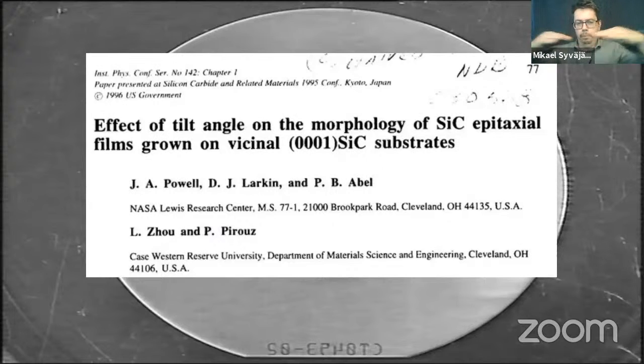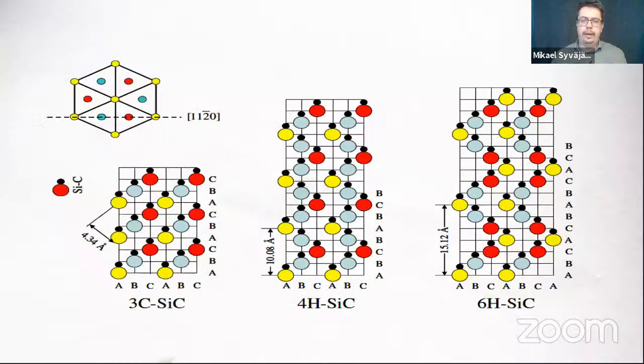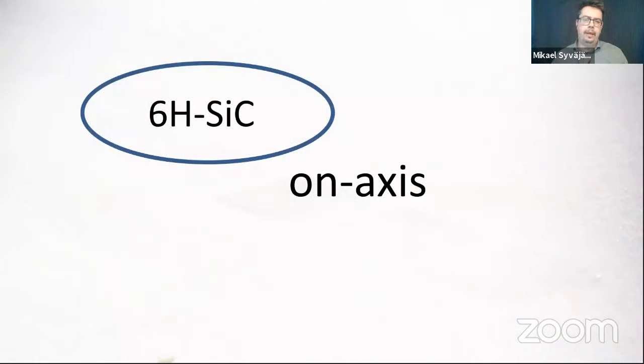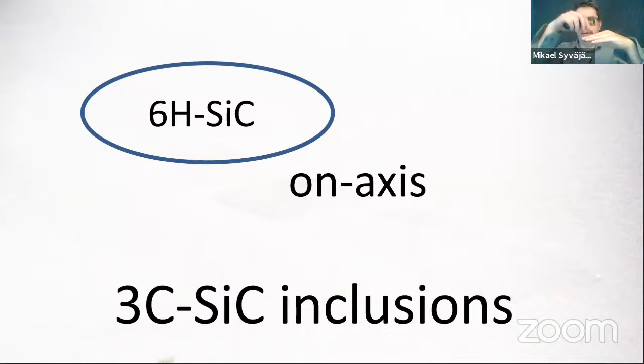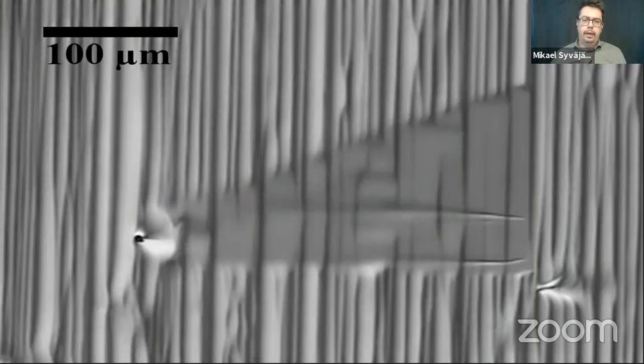carbide, you have a planar on-axis surface. But then when you have this planar, then you have different silicon carbide polytypes. So if we try to grow 6H or 4H, which are preferred for the power devices, then you also have other polytypes like the cubic silicon carbide. And when you grow on axis, for example, on silicon carbide, then you have inclusions of 3C in these layers. And that is, of course, not wanted. So then those create the disturbances in the growth, and then you cannot make devices on these ones.